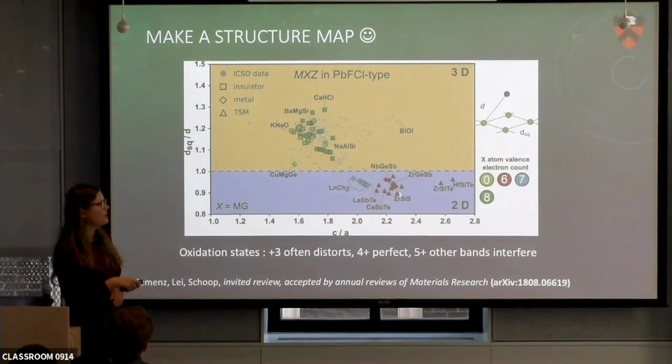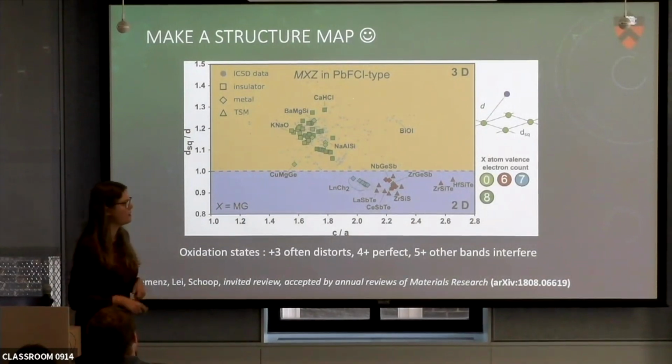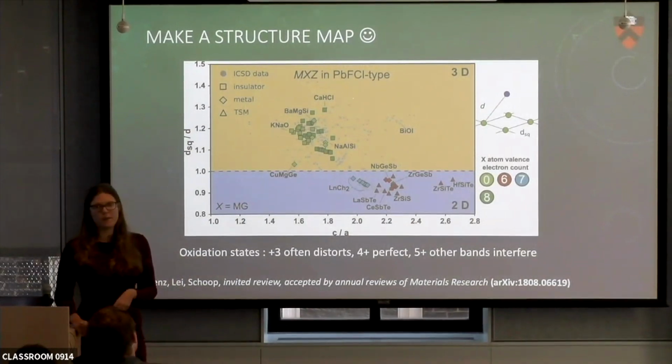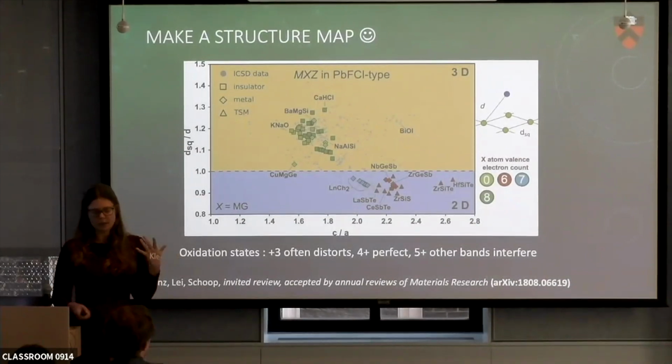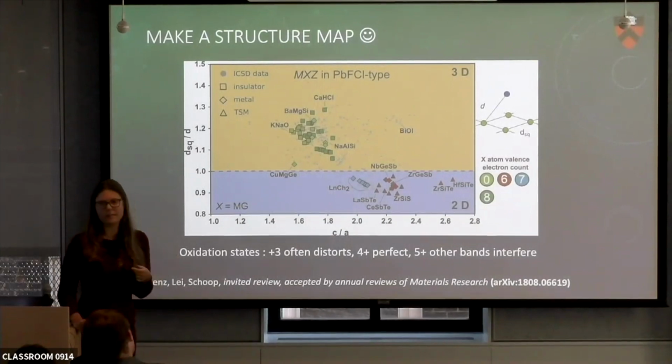And then these gray data points are all the materials listed in the ICSD, and the colored data points are the ones where, when we looked up band structures in the Materials Project, we gave them some credibility because these compounds aren't magnetic, and their optimized structure was the same as the structure in the crystallographic CIF file.